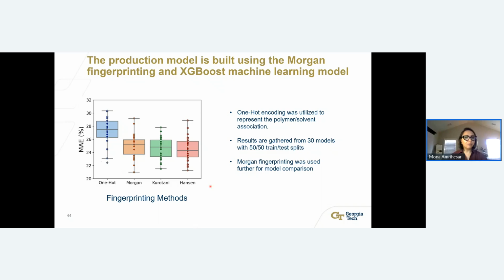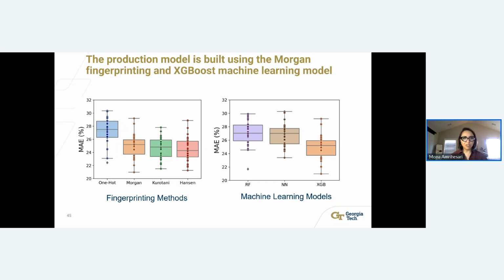As you see in this plot, there is not much difference between the Hansen solubility parameters, which is familiar for everybody, or Kurotani, which is some chemical and physical properties, to Morgan, which is based on the chemical structure of the solvent. So mean absolute error is almost the same for these three, and the one-hot coding has a little bit higher error. So we picked Morgan fingerprinting because we thought that it gives more information on the chemical structure of the solvents to the system. I don't share a lot of details in the machine learning to keep the story going and flowing, but if you're happy to discuss this, I'm happy to have another call or answer some of the questions.